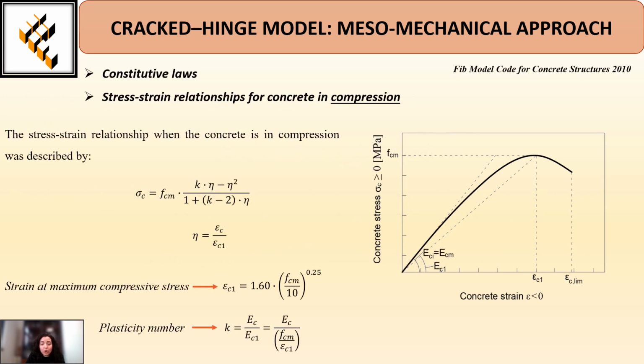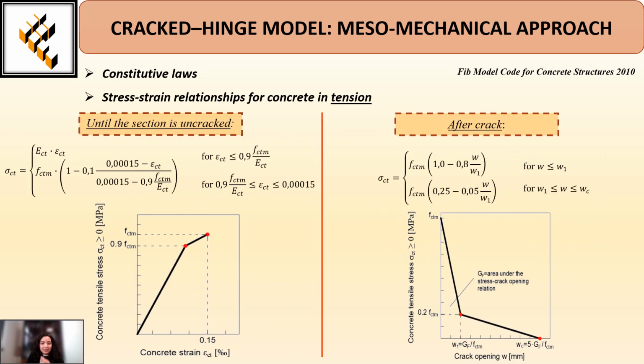For the constitutive law, we refer to the fib Model Code for concrete structures. In particular, the concrete behavior in compression is described by this equation, that is related to the strain at the maximum compressive stress and the plasticity number. To describe the tensile behavior, a stress-strain diagram should be used for the uncracked concrete, and a stress-crack opening diagram, as shown in this second figure, should be used for the cracked section.